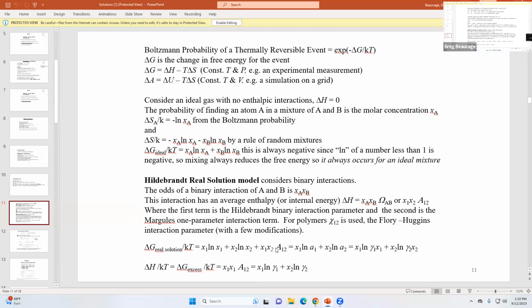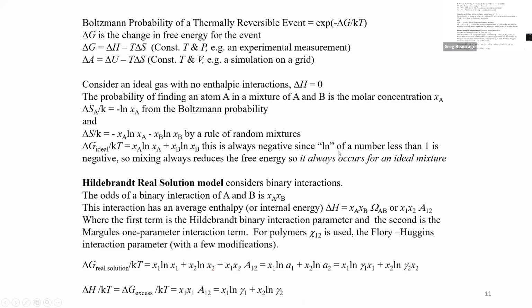And so it's a combination of the enthalpic interactions that are maybe opposing mixing, and the entropic term, which favors mixing. This favors mixing. This has a disfavor. This thing's 1/T, so as the temperature drops, this becomes larger, and then it dominates over that, and you get demixing at low temperature. That's called a UCST because you have phase separation as you cool it. So the critical point is at the upper part of the 2-phase boundary. So it'd be a UCST system, and just straightforward. All right, so there's that business.